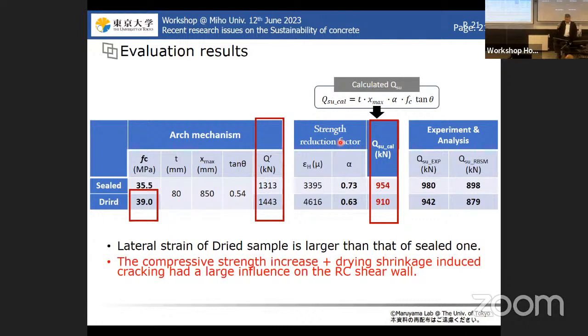So therefore, if the compressive strength of concrete is reduced by the drying, it is quite possible that the loading capacity is reduced by just drying. And today I couldn't talk in detail about how the compressive strength is affected by the drying, but if we use a certain kind of aggregate, especially non-shrinkable aggregate, in this case, we see the reduction of the compressive strength. But if we use an aggregate which is quite shrinkable, meaning an aggregate which contains clay minerals, we see the increase in compressive strength after the drying.